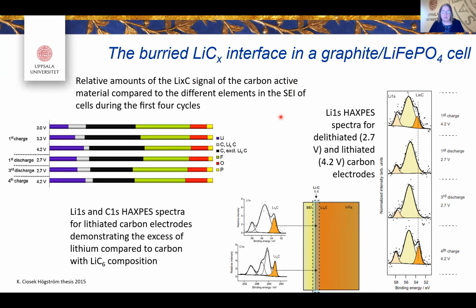In this system, we also actually try to say something about the buried interface, and that you can do by really looking carefully at different cycles and the kind of signals you have for both lithium and carbon. Also, you can see just by the general composition from the surface spectra that you do have quite a dynamic situation where this SEI is changing, if it's intercalated lithium or deintercalated lithium. So if you do your calculations correctly, you can actually find that in a fully normal and well-cycling system, you actually have a piling up of lithium ions here at the interface underneath the SEI and on top of the graphite. And you form, in this case, a composition of 1-to-1.